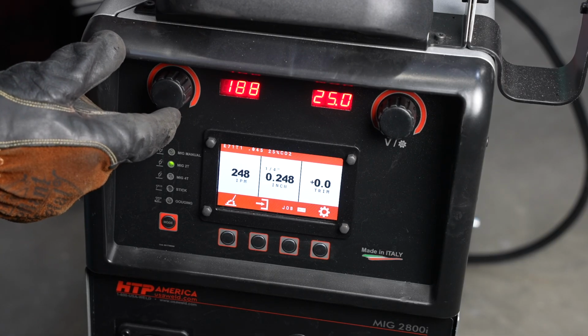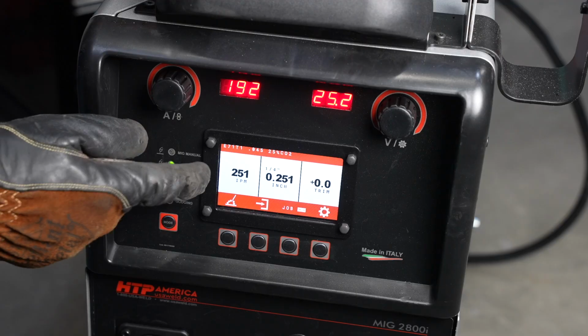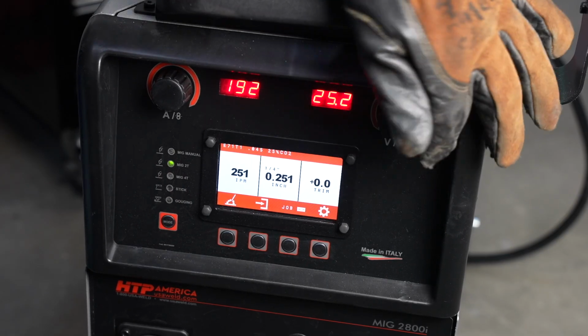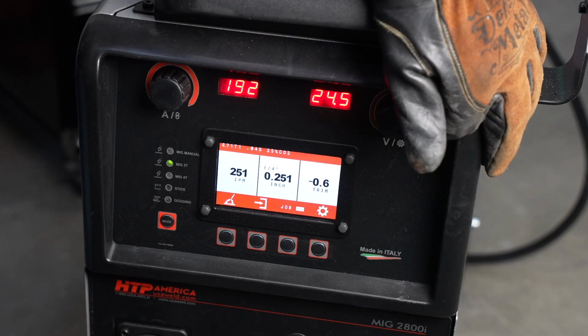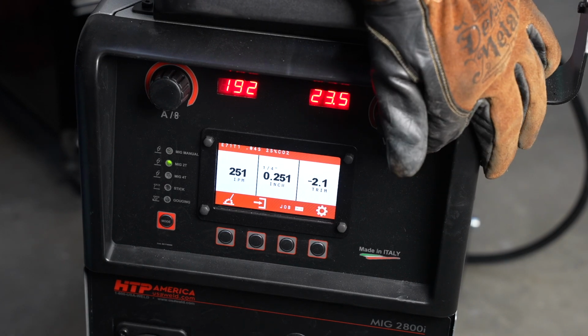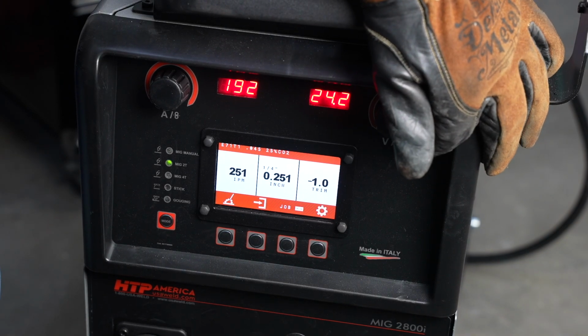So this is what I set it to right here, about 250 inches per minute. And since I was running vertical up on that last weld, I just dialed it back about a volt or so from what was recommended, and that worked really well for me. I probably didn't even need to dial it back, but it was helpful.